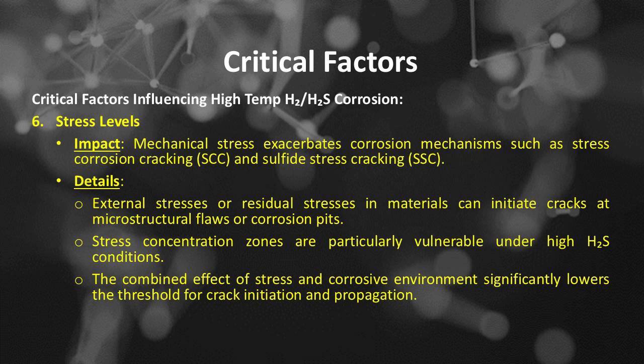Critical factors. Number 6 is stress levels. The stress levels impact: mechanical stress exacerbates corrosion mechanisms such as stress corrosion cracking, SCC, and sulfide stress cracking, SSC. For details, external stresses or residual stresses in materials can initiate cracks at microstructural flaws or corrosion pits. Stress concentration zones are particularly vulnerable under high H₂S conditions. The combined effect of stress and corrosive environment significantly lowers the threshold for crack initiation and propagation.